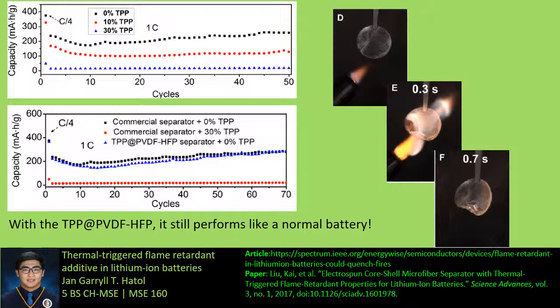This clearly shows the minimal difference between the no TPP and the thermal triggered flame retardant capacities. This means that the ones with thermal triggered flame retardants perform almost as if it had no TPP in the electrolyte. The images on the right demonstrate how effective the thermal triggered flame retardants are at quenching the fires. The images show the actual separator wetted by electrolytes. They show that at around 0.7 seconds after the fire starts, it's almost immediately quenched.